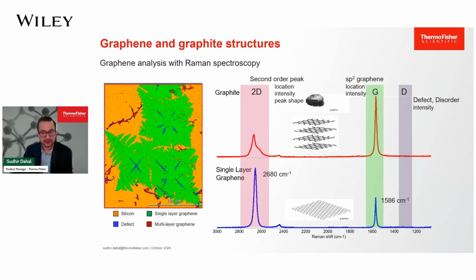Another significant aspect of Raman spectroscopy is its ability to identify single-layer graphene through the intensity ratio of the 2D band to the G band, as shown here. For instance, when the intensity ratio of the 2D band, also known as the G prime band, to the G band is 2, it does indicate that there is a single layer graphene present. So again, Raman spectra can be really powerful in giving that kind of information.